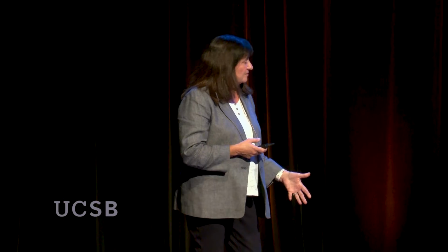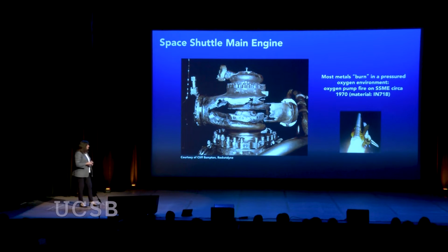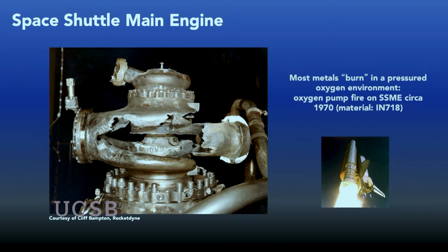If you fast forward a little bit from the Saturn rockets and the Apollo environment to the Space Shuttle main engine and more modern rockets that take off at Vandenberg, it seems like almost daily, there are different challenges as they become more advanced. And here's an example of another challenge. This is the oxygen pump that is just above the nozzle in the main engine. You can see that after a test, this nozzle is completely gone. It has burned in the high-pressure oxygen environment. And so it was a major challenge to find materials that would survive in those sorts of environments to make these more advanced rockets possible.